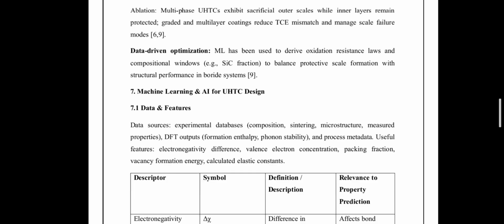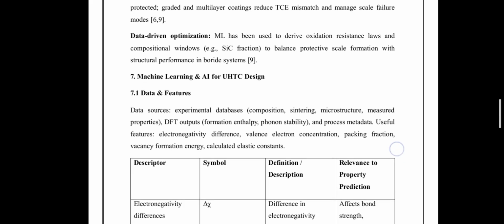Next is the machine learning and AI for ultra-high temperature ceramics. Their data and feature engineering. Modern ultra high temperature ceramics design increasingly relies on data driven approaches to complement experiment and DFT predictions. The key data sources include experimental databases: composition, sintering condition, microstructure, measured properties, and DFT outputs. There is formation enthalpy, phonon stability, elastic constants, and the process metadata, that is their temperature profile, atmosphere, precursor type, etc. The crucial descriptors that we feed in our machine learning for the synthesis and design of our ultra high temperature ceramics are as follows.